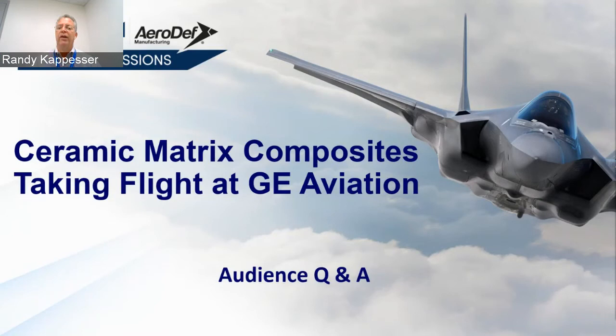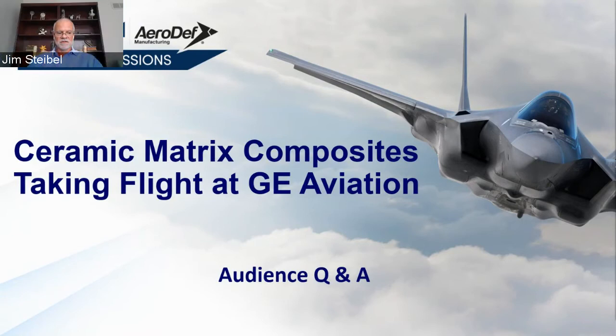Yeah, that's a great question. I kind of touched on the ability to do it. Didn't get into specifics on what's allowed, but just looking at the fracture behavior of ceramics in general, their high sensitivity to voids and defects and pores really translates in a composite world to impacts to our interlaminar strengths. So we really do have to get a dense material. And that's part of what makes our technology unique. That's part of why GE has CMCs in engines and others don't, as other CMCs typically have a fair amount of porosity in them, and that limits their ability to use them in an engine. So quantifying that, having a process to do it, but also a means to inspect and control is really critical to using the material.